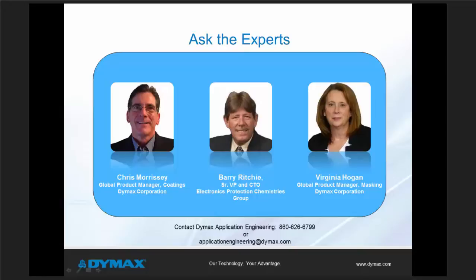Let's see. Are these light curable conformal coatings compatible for use on multi-layer PCBs with micro vias? Absolutely. One of the most difficult parts of any conformal coating process is actually getting the coating on the sides of the board. I've had cases where I've had over 16 layers of backplane circuitry all tied into each other. Most customers will only coat top and bottom, depending on the type of side edge rail conveyor that you're using. So it is kind of important to try to get some of that coating on the actual edges of the board itself to prevent delamination of the individual laminate layers.